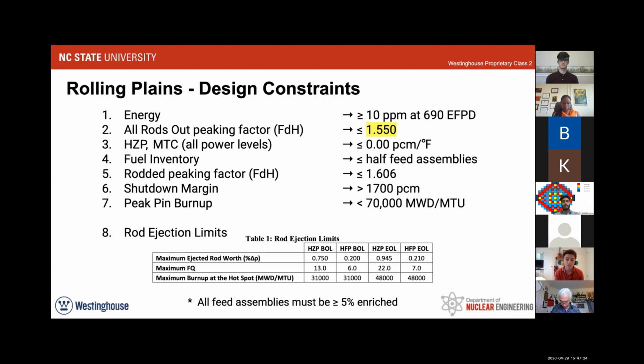Our peak pin burnup is less than 70,000 megawatt days per MTU. So that's above a standard burnup that you would typically allow for. So what we did for this project is, because it's high enrichment and high burnup, we pretty much pretended that the NRC would allow for a little bit higher burnup, as that's kind of where the industry is going. And so an additional note was all the feed assemblies that we would put into the core had to be greater than or equal to 5% enriched. And that just also helped us to get by with the energy requirement. And then finally, we had the rod ejection limits. We'll talk about this a little bit more later, which is really important for the safety checks.